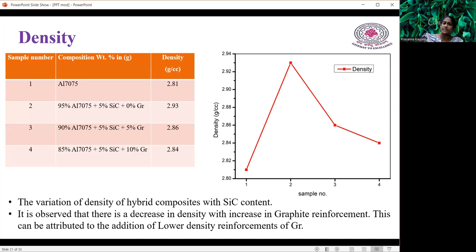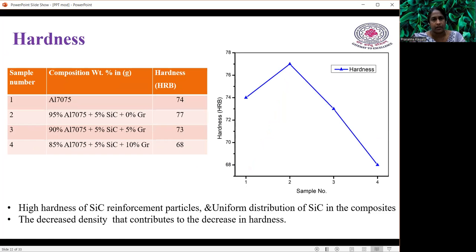As far as the density is concerned, single aluminium 7075 has 2.81, and if you add graphite at 0, 5%, 10% with a fixed amount of 5% silicon carbide, the density goes on decreasing. That means there is a decrease in density with the increase in graphite reinforcement. So the lower density of graphite reinforcement can be concluded. As far as the hardness is concerned, hardness also decreases as the graphite content is increased.